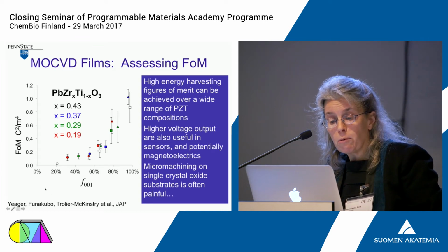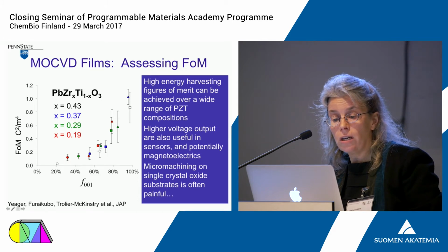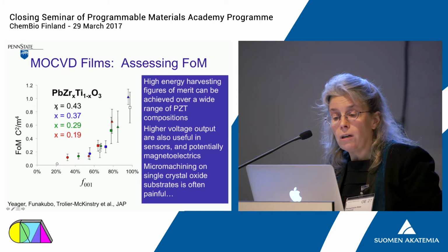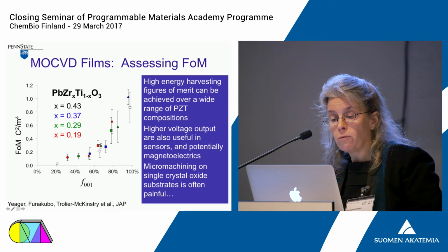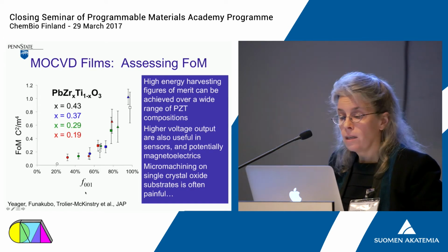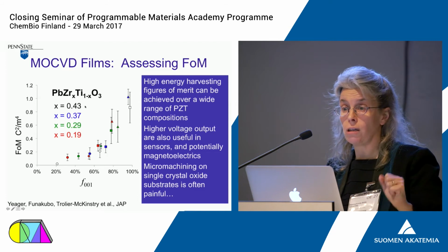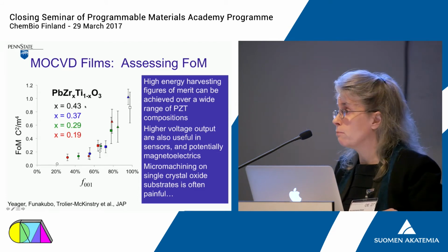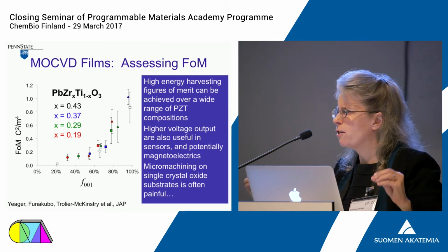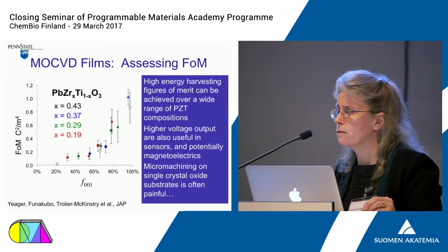So working with the group of Professor Hiroshi Funakubo of Tokyo Institute of Technology, one of my students grew lead zirconate titanate films from actually quite a wide variety of compositions, and here's the amount of polarization we get out of plane, and here's the figure of merit, and experimentally you actually achieve that full order of magnitude improvement in the figure of merit. Very interesting. Let's go build a mechanical energy harvester out of this.